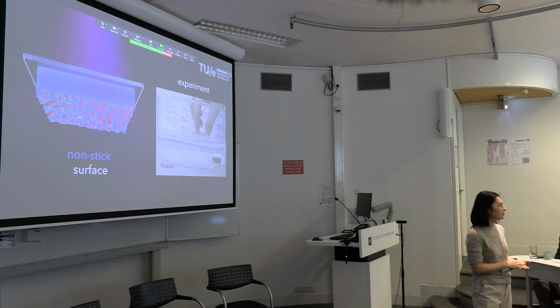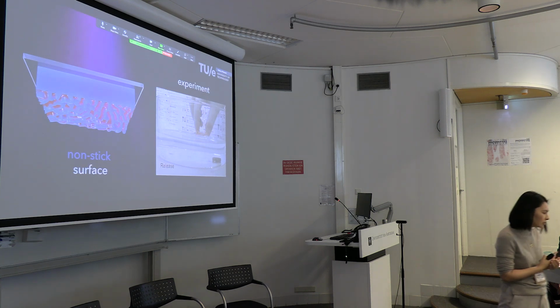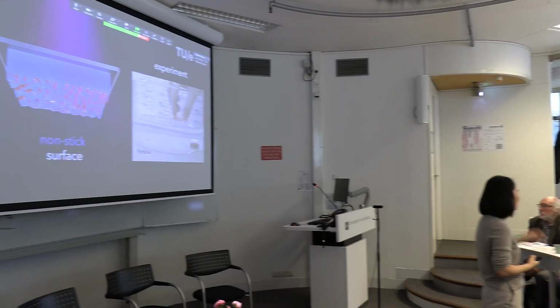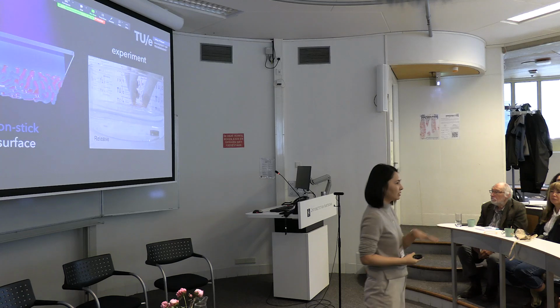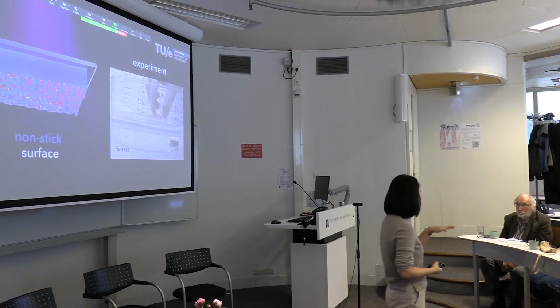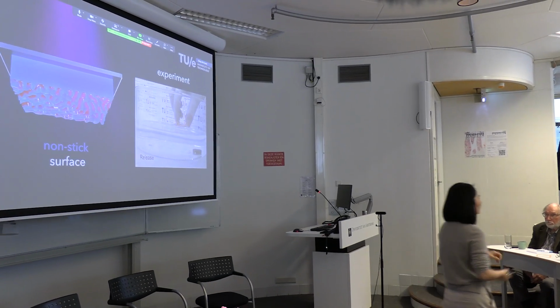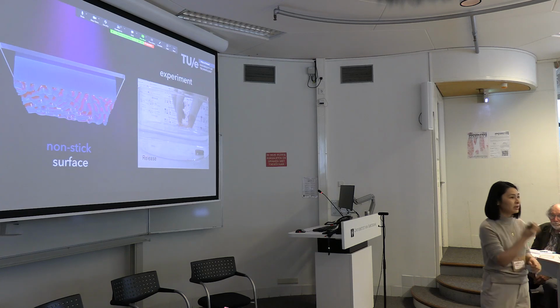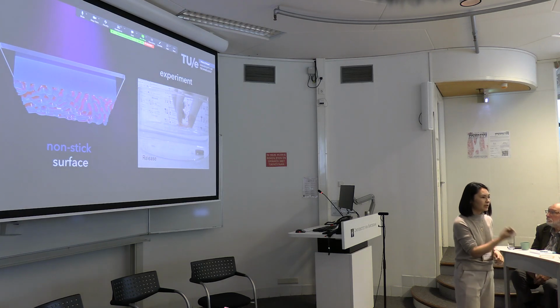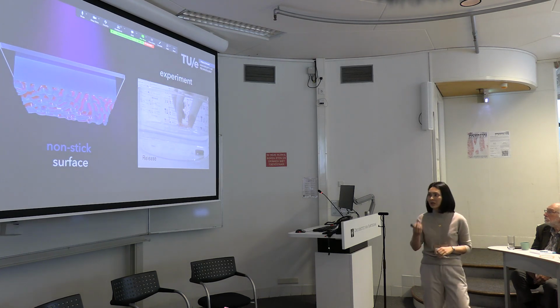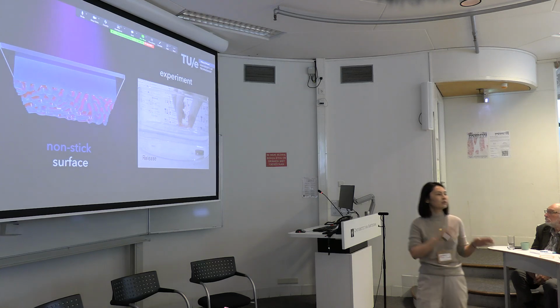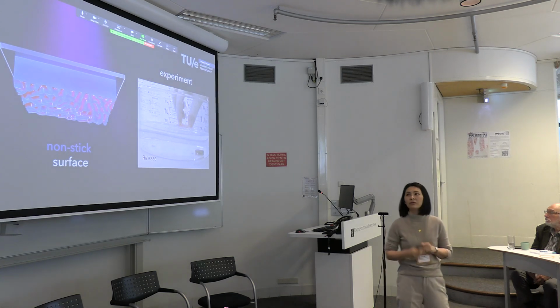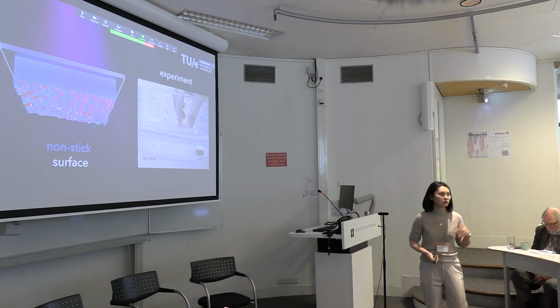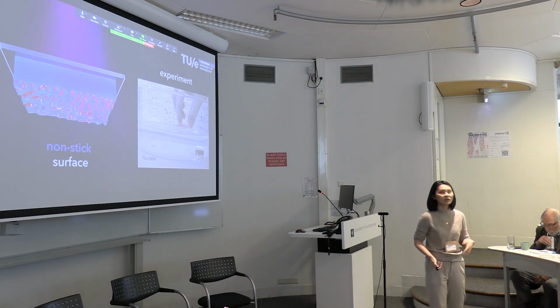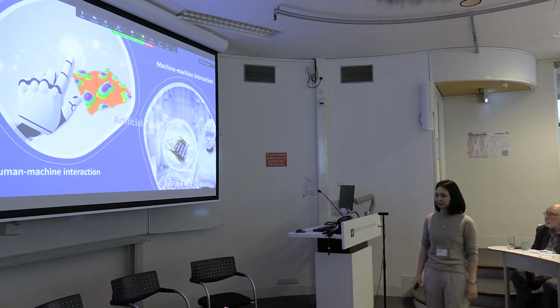We developed this to provide an alternative solution for the pick-and-place system in industry. Pick-and-place systems in industry always use vacuum, but vacuum can damage many delicate components like optical devices and semiconductor devices. They are really looking for an alternative for that reason. So we propose to switch the surface from stickiness to non-stickiness in this case.